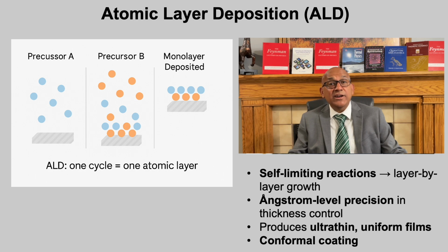Another unique advantage is that ALD produces highly conformal coatings, even over rough, porous or three-dimensional surfaces, such as nanopores, nanotubes, or complex device geometries. This makes it indispensable for microelectronics, protective coatings, and energy storage devices like lithium-ion batteries.